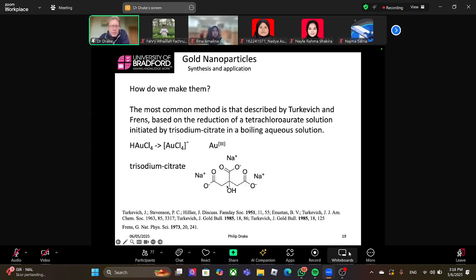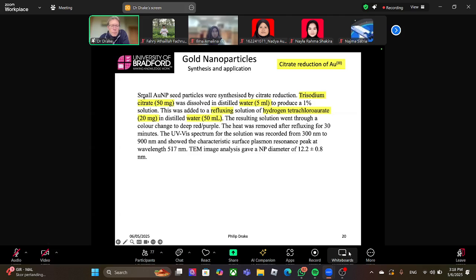You take trisodium citrate, citric acid, the sodium salts of that. We've got 3 carboxylate groups. This is a very strong reducing agent. So we take trisodium citrate, around 50 milligrams, dissolved in water, about a 1% solution. You add this to a refluxing solution of hydrogen tetrachloroaurate, 20 milligrams, in water. The solution will go through a colour change. It'll go from being a yellowy, orangey colour to a deep red purple colour.